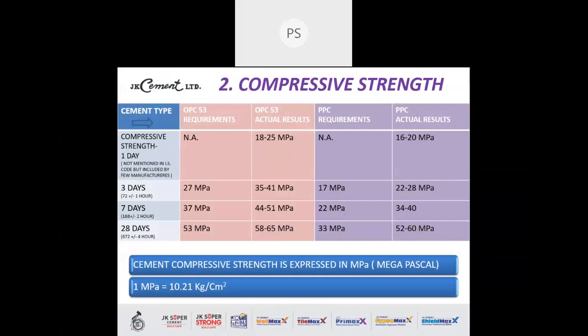3 days minimum strength should be 27 MPa. We get a strength of 35 to 41 MPa in India. 7 day, 37 MPa. We get a strength of 44 to 51 MPa. And 28 days, which is also called the ultimate strength, should be minimum 53 MPa for OPC 53. We get a strength range of 58 to 65 MPa.